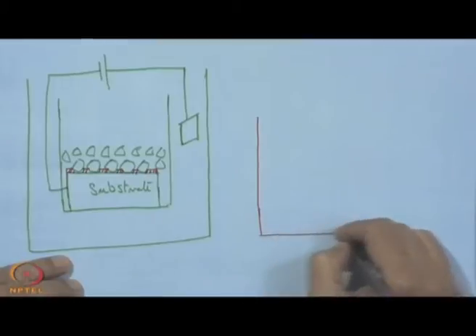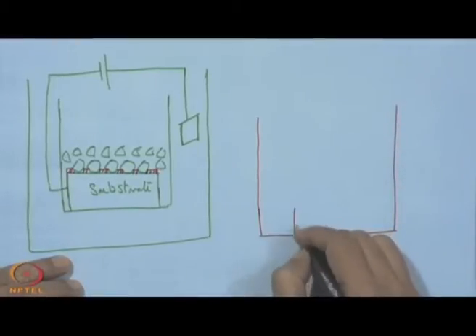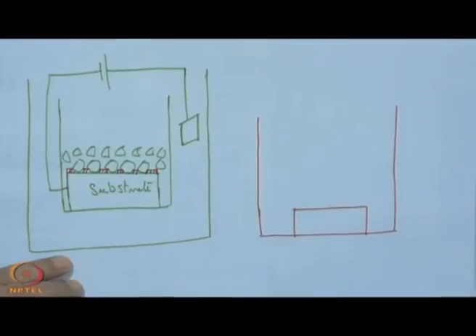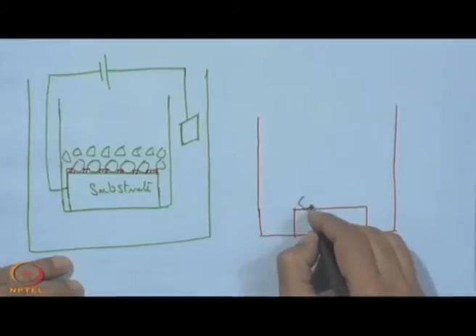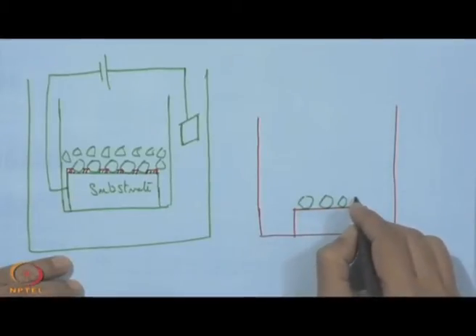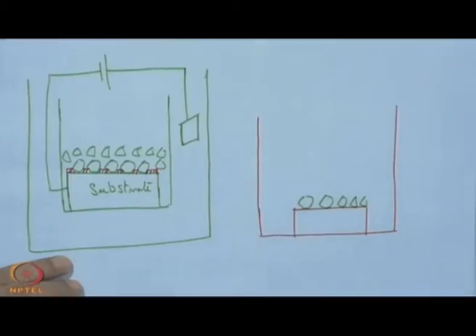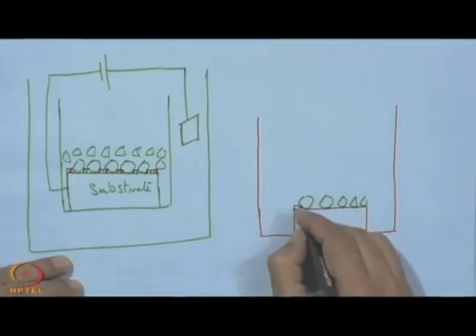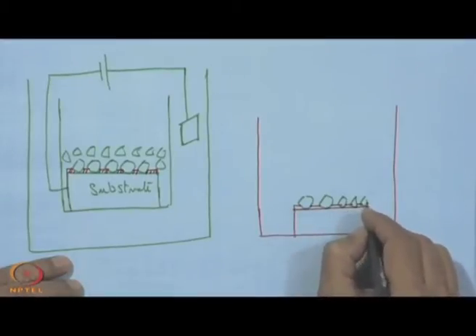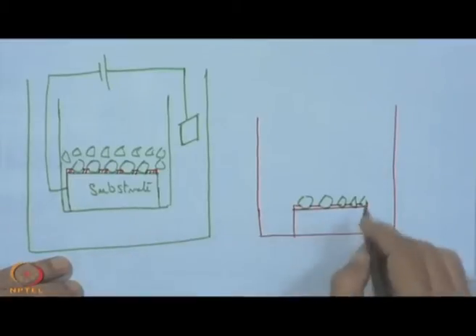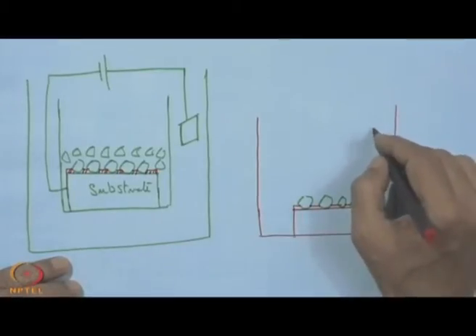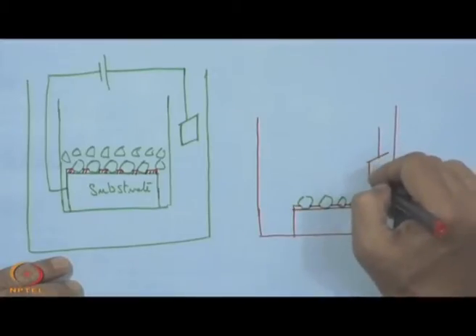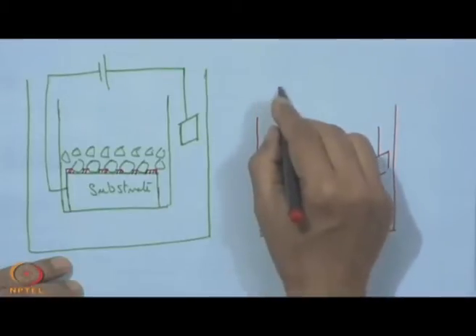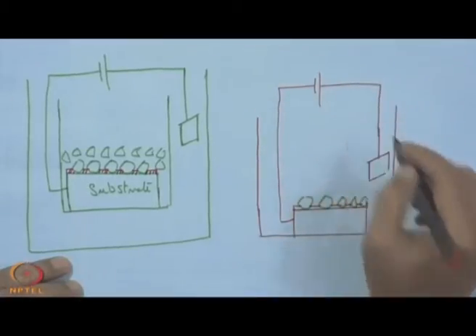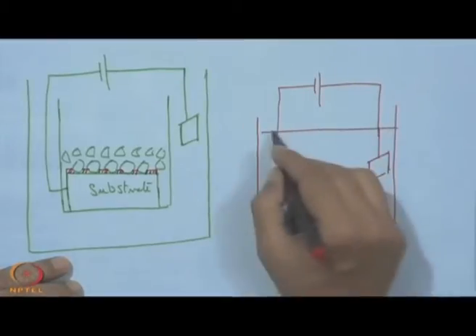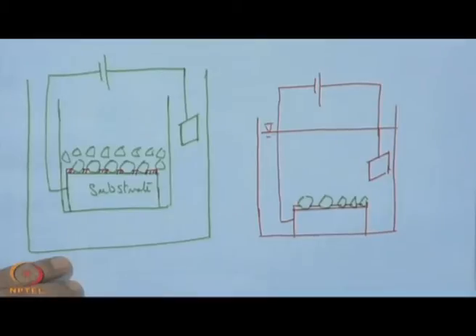So, electroplating means this one, and here what we have, this is the substrate where the grits are already anchored, however, with a very weak holding force. So, this is the level of the grit, level of the bond material, which is the outcome of this tack down process. And now, over that, with this cathode anode action, we have heavy metal deposition over this surface, and that will be built up over this.